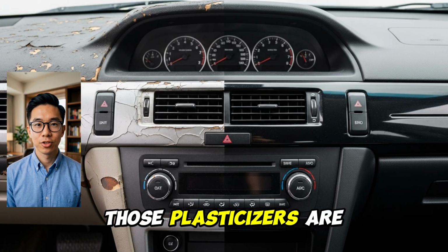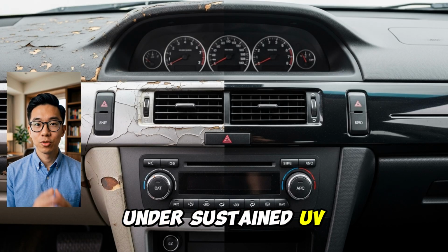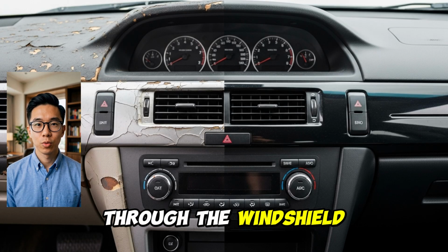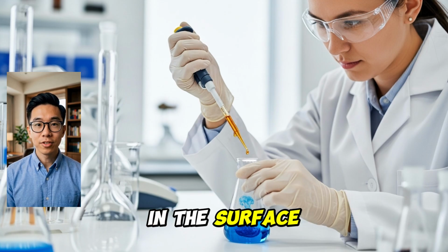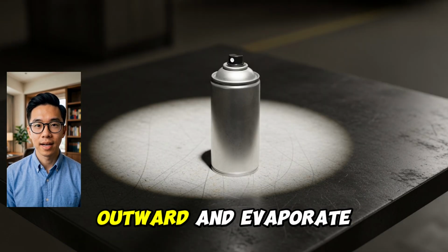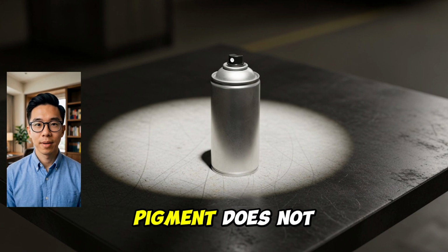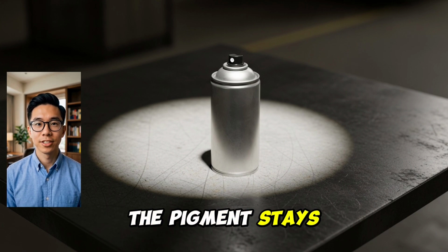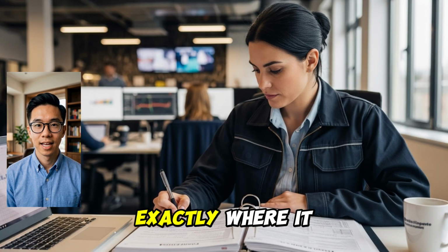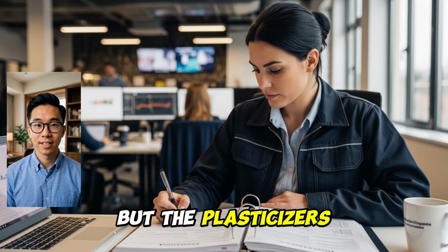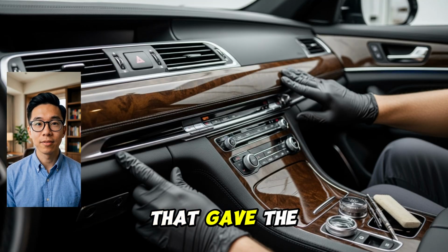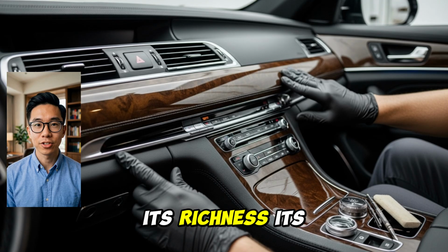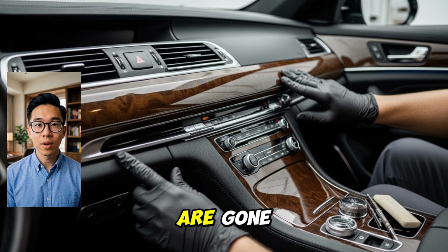Those plasticizers are volatile. Under sustained UV radiation from direct sunlight through the windshield, the ester bonds in the surface layer of the plastic begin to break. The plasticizers migrate outward and evaporate. The carbon black pigment does not move. The pigment stays in the polymer matrix, exactly where it was put. But the plasticizers that surrounded it, that gave the surface its depth, its richness, its wet black clarity, are gone.